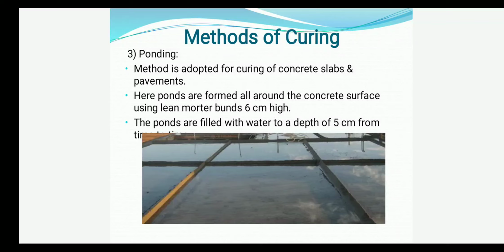The third curing method is ponding. This method is mainly adopted for curing of concrete slabs and pavements. Here, ponds are formed all around the concrete surface using lean mortar bunds 6 cm high.